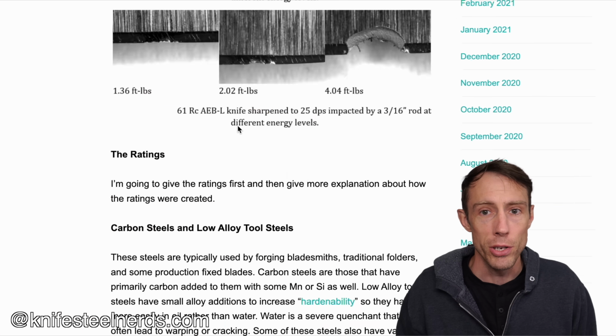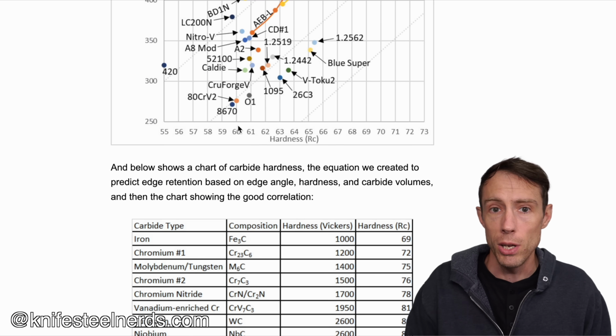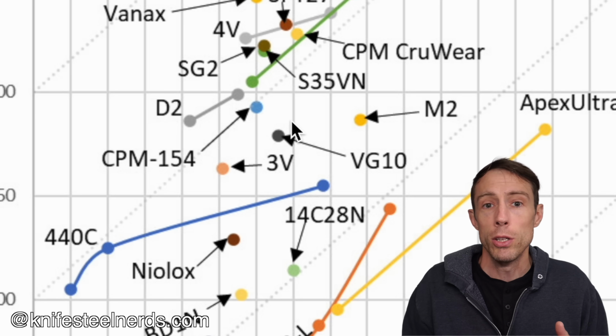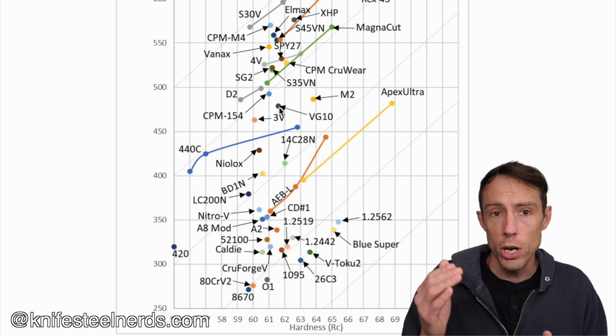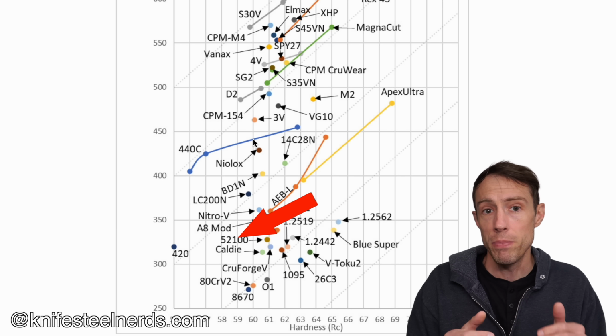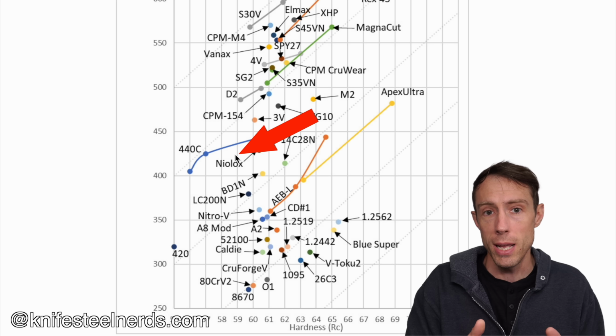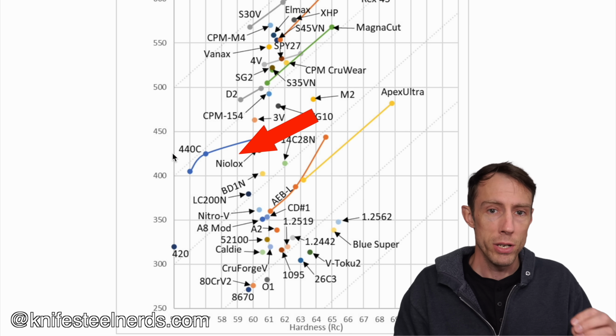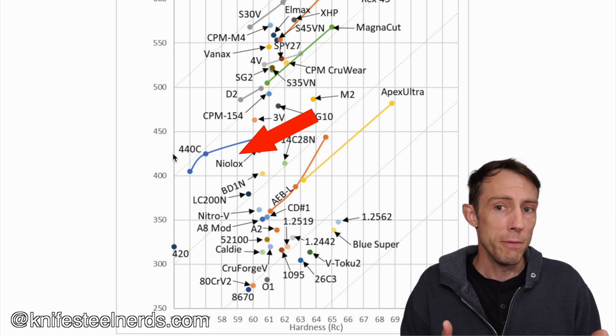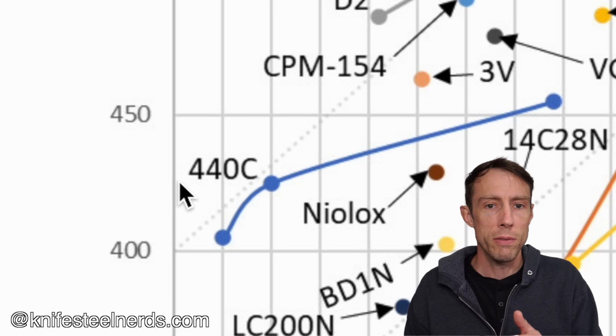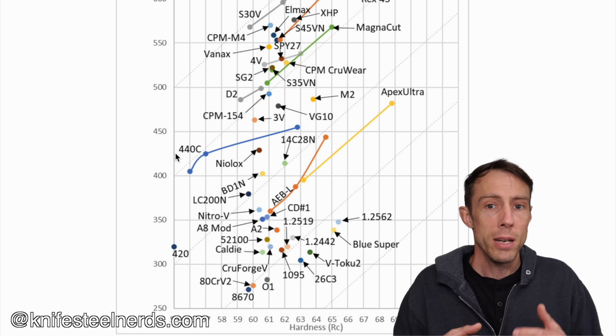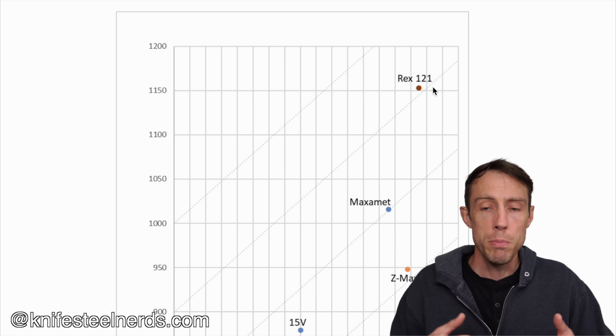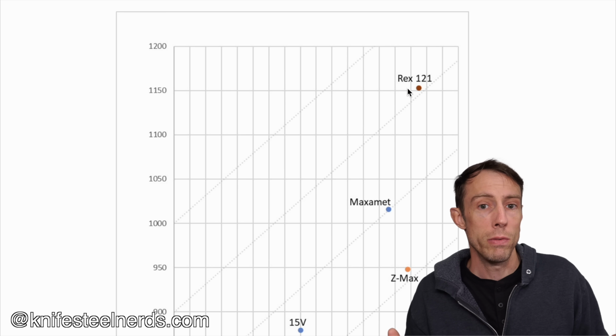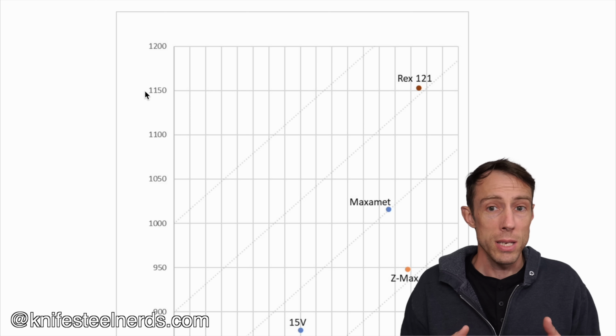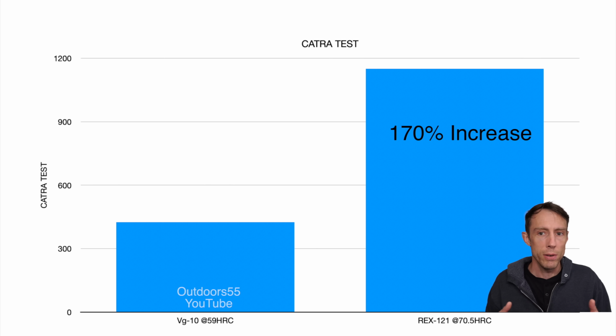If we go to the Knife Steel Nerds edge retention chart, which I will link below, definitely go check out Knife Steel Nerds, and we look at the VG10, we follow the chart down to about 59 HRC. That's how this chart works. We can follow the chart down to a specific hardness and get the predicted edge retention data. It looks like VG10 would score about 425 cuts at around 59 HRC. Now if we look at Rex 121 at 70.5 HRC, we're getting a touch over 1,150 cuts. So this equals about a 170% increase in terms of edge retention between these two knives.